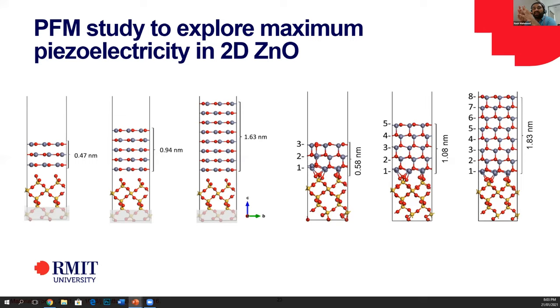Then we found that these can be very useful when we test their performance for piezoelectric coefficient measurements. They were very exceptional. They give us almost 8 times better performance. Then we wanted to find out why they are giving us such a high performance, so we did some theoretical studies. When we did the theoretical study, we found that ultra-thin zinc oxide is active.